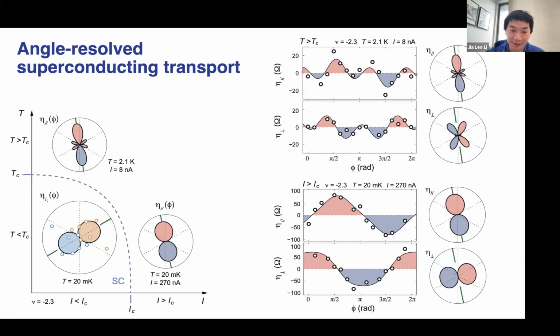What I'm plotting here is the value of the superconducting diode effect, or the non-reciprocity, the difference between critical current between forward and reverse bias. What's consistent is that it does confirm that rotational symmetry is broken, right? We get a close to one-fold symmetric response. What's interesting is that the mirror plane of the superconducting phase seems to be rotating from the normal state.